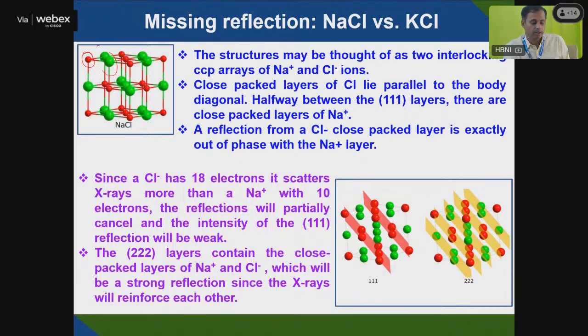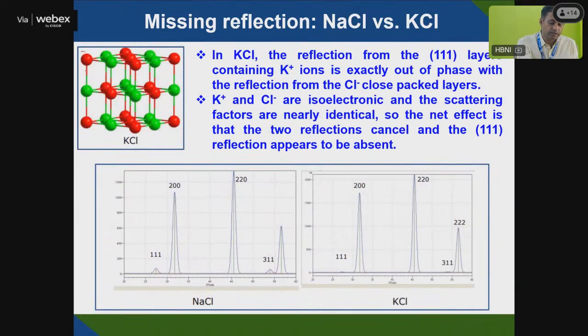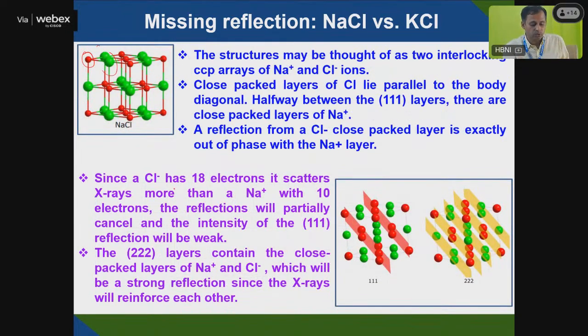In NaCl, the atoms are different in size. But if you see K and chlorine, these two, red and green, are almost equal in size. That means their Z value is the same, they are isoelectronic. Since chlorine has 18 electrons, it scatters X-rays more than sodium. Sodium has 10 electrons. For Na plus and Cl minus, to satisfy the octet, sodium has 10 electrons and chlorine has 18 electrons. So being 18 electrons, the reflection will be much higher in the case of Cl minus.